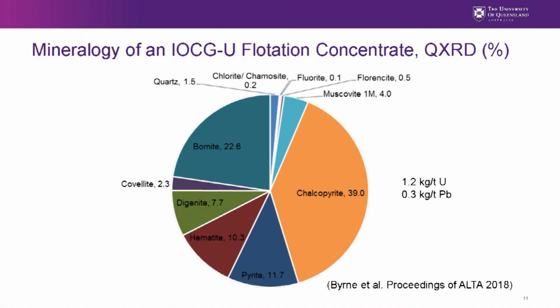So this is the mineralogy of an example of an IOCGU flotation concentrate using quantitative X-ray diffraction. And in this case, we see that the major phases are chalcopyrite and bornite. The other copper-bearing phases, digenite, covellite. Iron phases, hematite. The iron oxide is still there, even after flotation, pyrite. And the other gangue minerals still present, quartz and other silicates and fluoride minerals, present in still substantial amounts. From the assay, this is still about 1.2 kilos per ton uranium, 0.3 kilos per ton lead, and most of that lead is non-radioactive, lead 206.